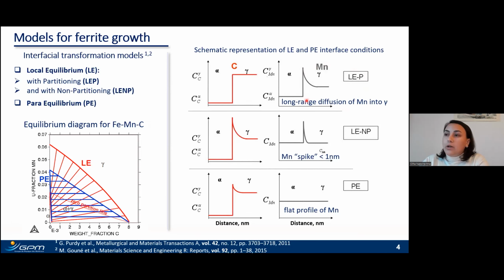In the case of local equilibrium with partitioning, the full equilibrium condition assumed to exist on the migrating interface requires the partitioning of the substitutional element, manganese in our case, across the transformation interface and into the gamma phase. In this case, kinetics is expected to be slow since it's mainly controlled by the diffusion of substitutional elements. In the case of local equilibrium with non-partitioning, only a spike of manganese less than a nanometer in width is expected to be observed at the interface in order to respect the local equilibrium condition. And the transformation in this case will be mainly controlled by the redistribution of interstitial carbon in our case, which means fast kinetics.